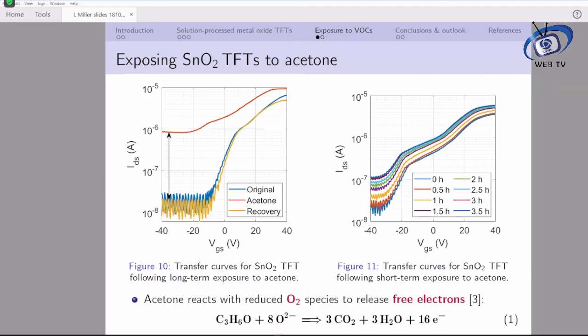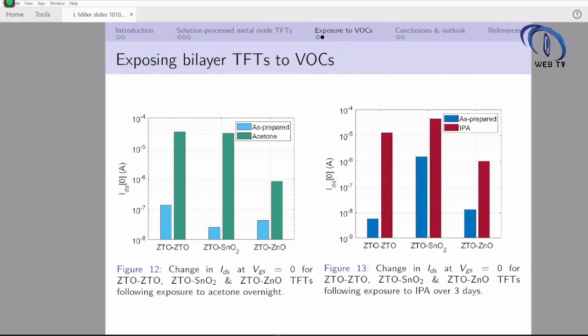Finally, bilayer thin film transistors annealed at 500 degrees Celsius were exposed to acetone and another reducing vapor, isopropanol or IPA. The second layer or open channel was varied to optimize selectivity. The 3 devices under test were therefore ZTO followed by another layer of ZTO, ZTO followed by zinc oxide, and finally ZTO followed by tin oxide thin film transistors.